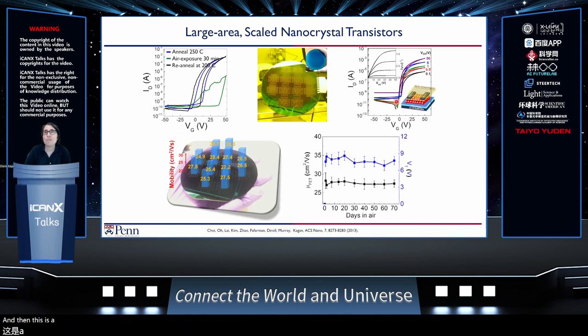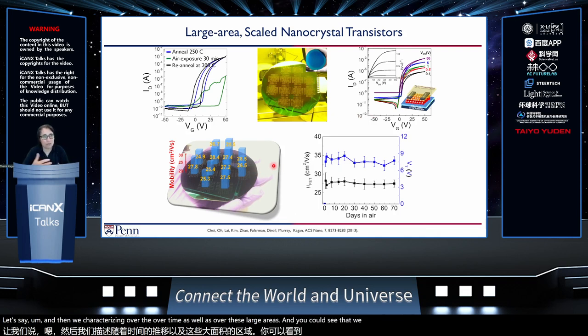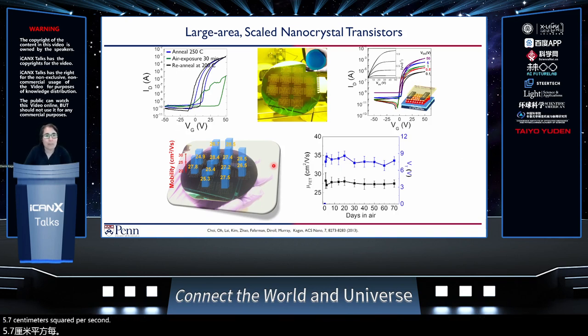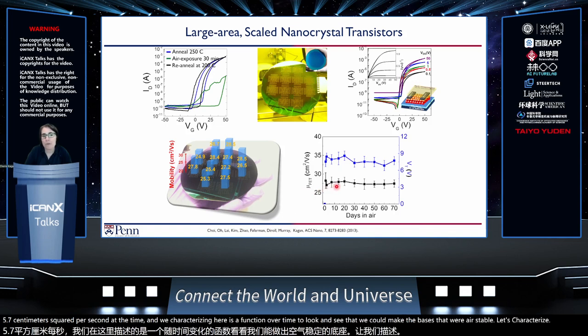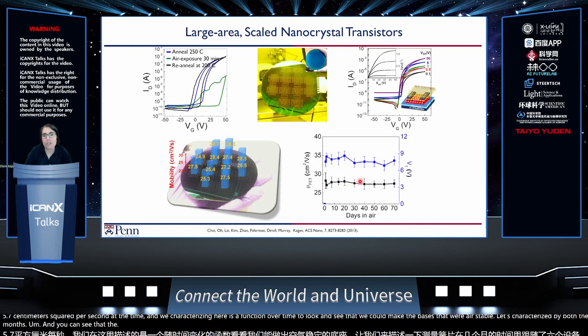And then this is an example of the kinds of characteristics of the devices that we would achieve, which are ones that look good. We characterized these over time as well as over these large areas. You could see that we could reproducibly have mobilities on the order of about 25 to 27 centimeters squared per volt second at the time. We also characterized these over time to see that we could make devices that were air stable. We followed half a dozen devices over a couple months, and you could see that the mobility as well as the threshold voltage of the transistor remained stable.